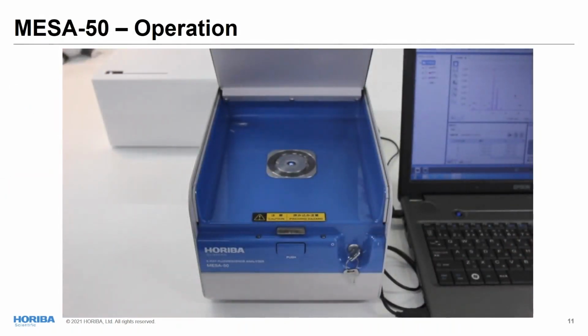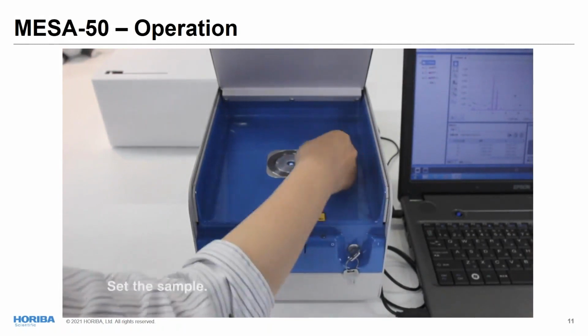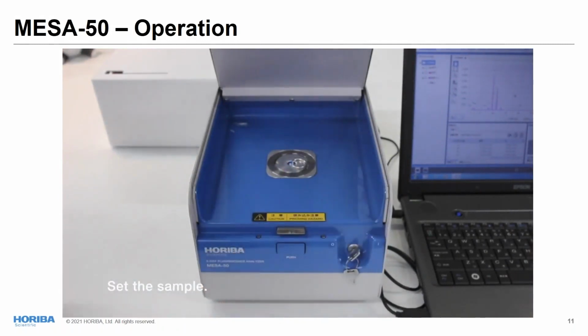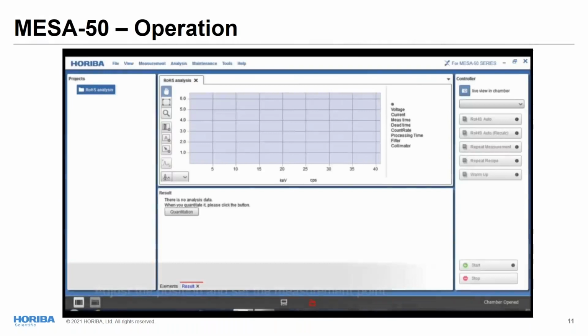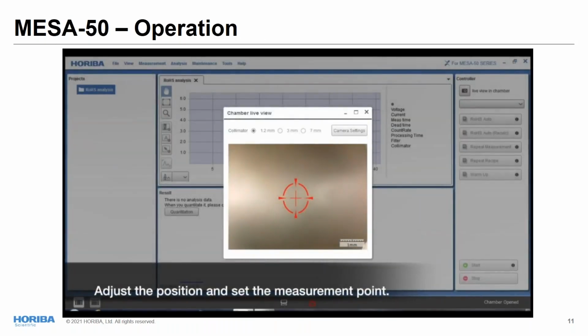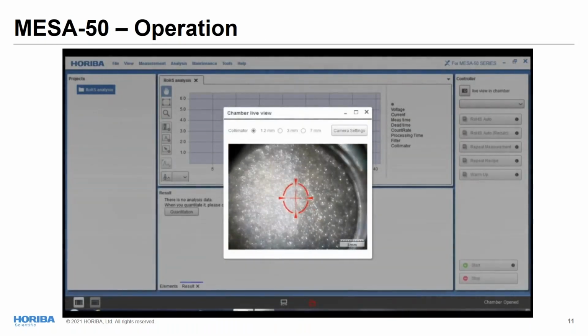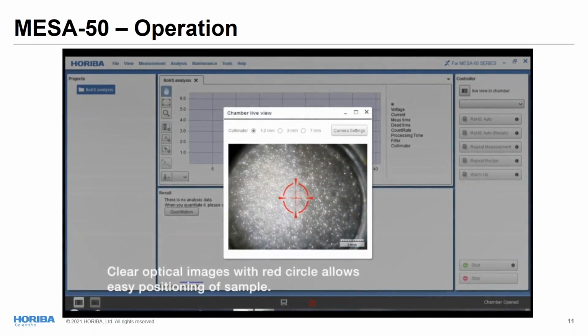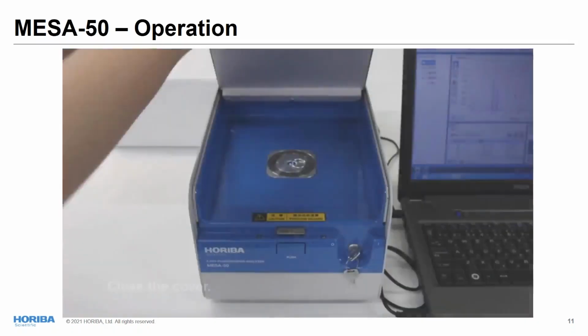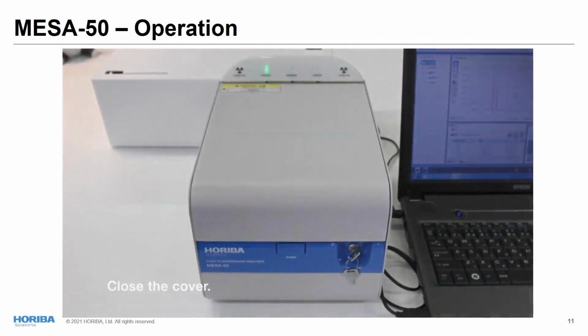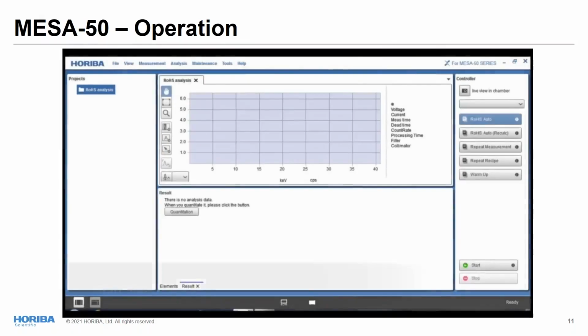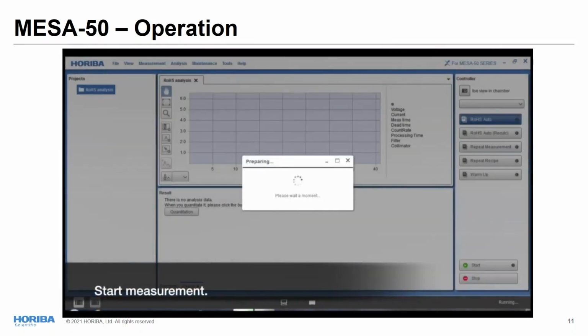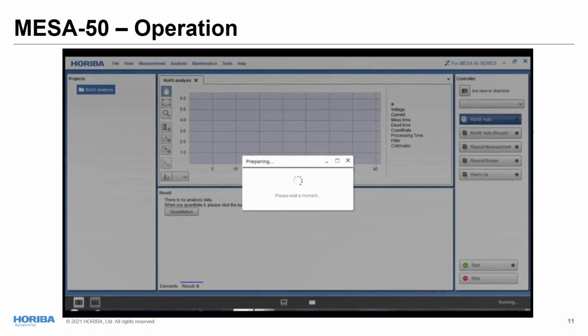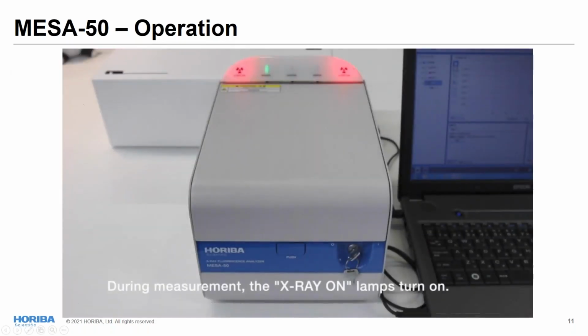Operating an XRF system is really straightforward. You can see in the video here. It's just about opening the cover, positioning the sample, solid, or if it's a powder, in a sample tray, and adjusting the position using the visualization screen in the software. From there, as soon as you have located your sample where you want, you close the door and just start the analysis in the software. Due to X-ray related regulation, of course, the system will warn you that the source is on. Those are these two red lights you can see. And from there, the analysis will start.